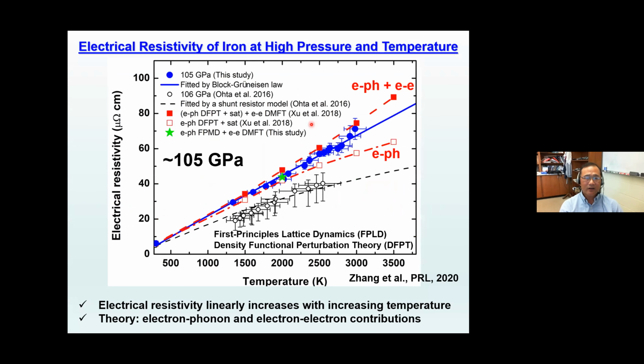So this is a set of our data at about 105 GPa for the electrical resistance of pure iron in the HCP phase as a function of temperature. So the blue dots here are our experimental data. So you see resistivity goes up linearly with increasing temperature, and that's expected for a pure metal.